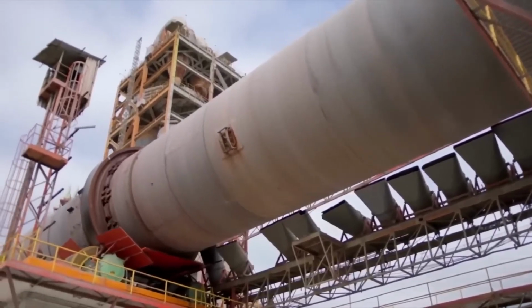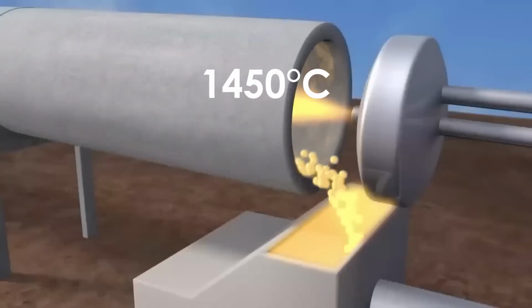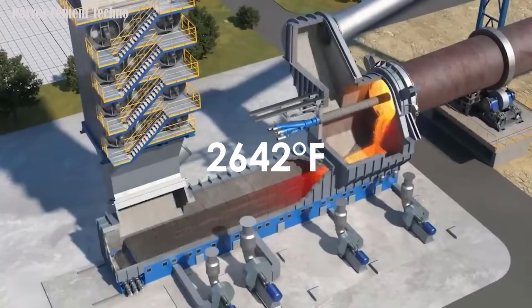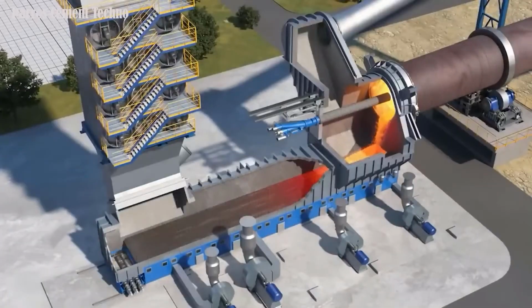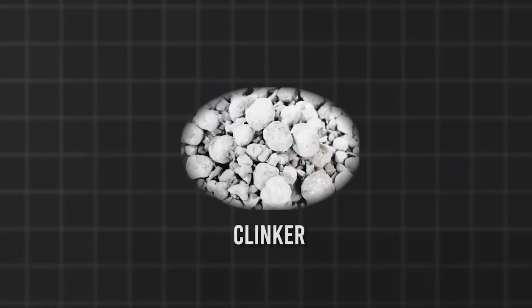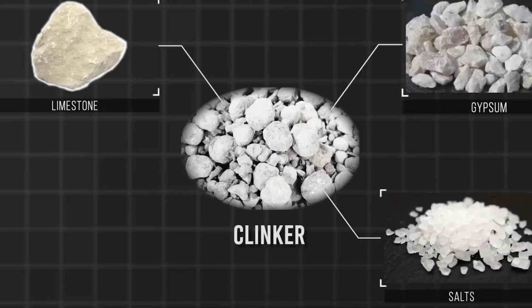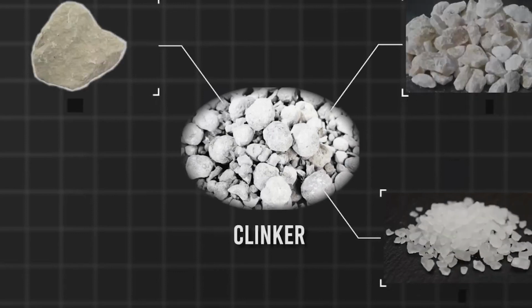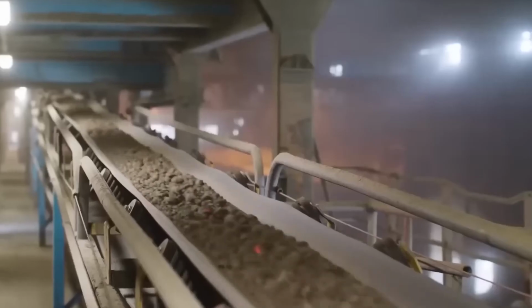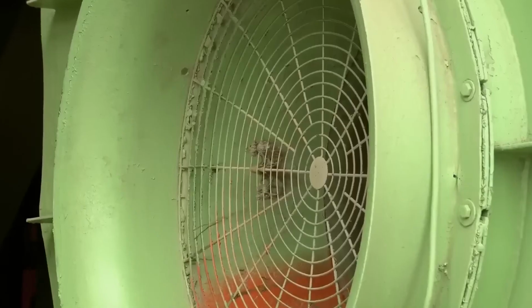A temperature of around 1,450 degrees Celsius, which is equivalent to 2,642 degrees Fahrenheit, is reached within the kiln. The raw materials are subjected to a series of intricate chemical reactions and sintering activities within the kiln, which ultimately results in the development of clinker, which are nodules that are about the size of marble. After being expelled from the kiln, the clinker, which is composed of calcium silicates, aluminates, and ferrites, is next transported through a clinker cooler. The cooler forces air across the clinker, which lowers the temperature.